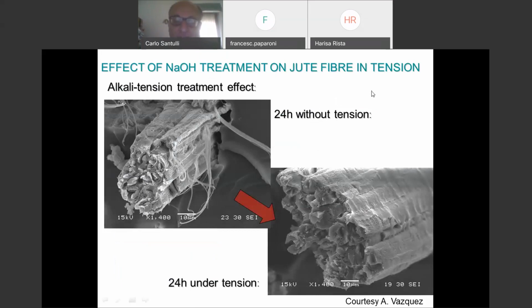with jute fiber. This is jute fiber, and you can see that it's more irregular than hemp, for example, and here is shown the effect of alkalis, of sodium hydroxide, together with tension. So it was observed that the effect of regularization obtained by sodium hydroxide was enhanced if you put the fiber also under tension. This is an idea of the work which is done with this kind of fibers.